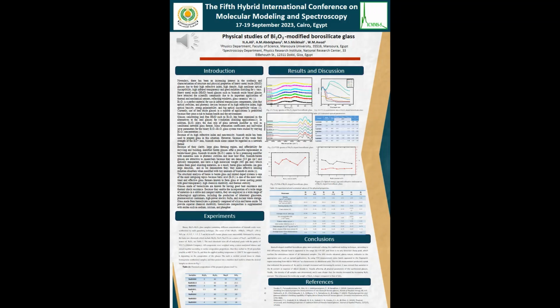Hello everyone, now I will present my research, which is entitled Physical Studies of Bi2O3 Modified Borosilicate Glass. In this research, a glass sample of composition x Bi2O3, 60 B2O3, 10 Na2O, (30-x) SiO2 mole percent was prepared via the melting technique. X-ray diffraction was applied to prove the amorphous nature of the prepared glasses. UV-visible absorption spectra were measured in the range 200 to 1100 nanometers, which were applied to evaluate optical properties, including direct and indirect optical energy band gaps.